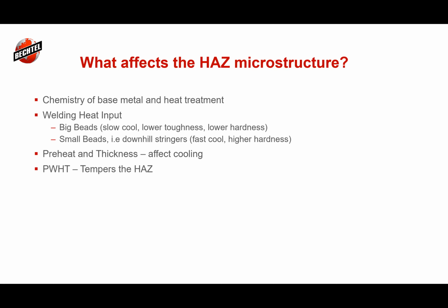With welding heat input, whether you have big beads where you're having slow cooling, it typically, not always, will lower your toughness and lower your hardness. And then when you have small beads, there are downhill stringers. When I first started in the industry 27 years ago, in some of the structural steel in the tanks, it was really common to do vertical 7018 up, and then they were doing 6010 downhill stringers on the side, particularly for welders that weren't as good, because they would cover over their undercut. And I think that's gone away.